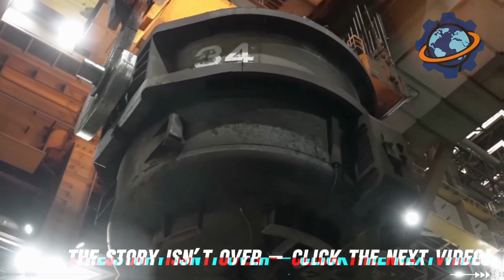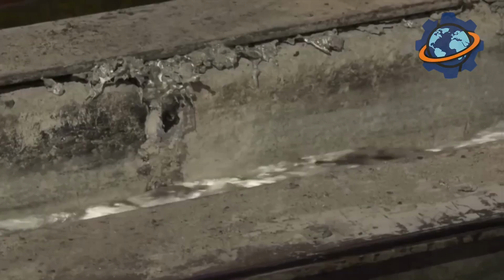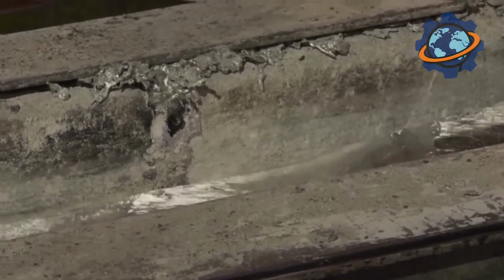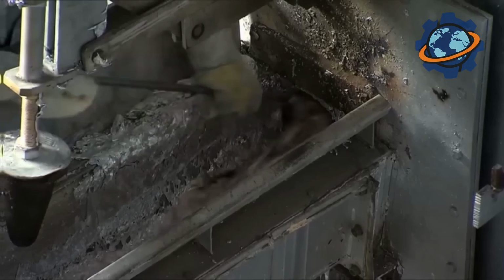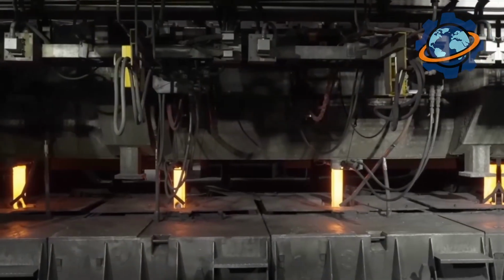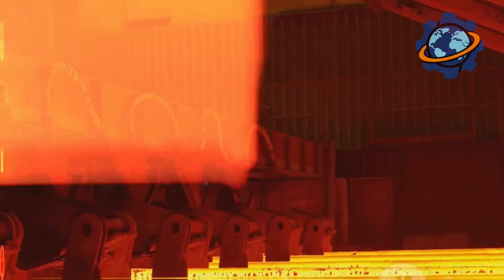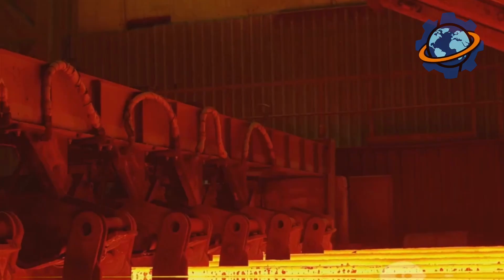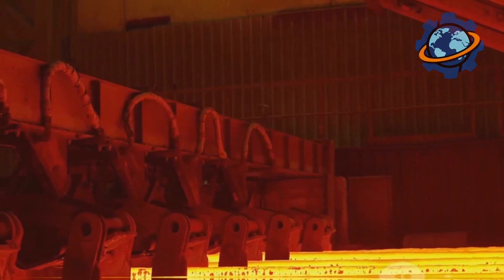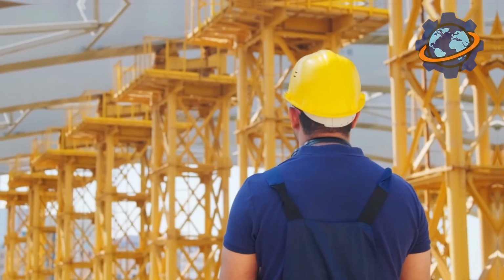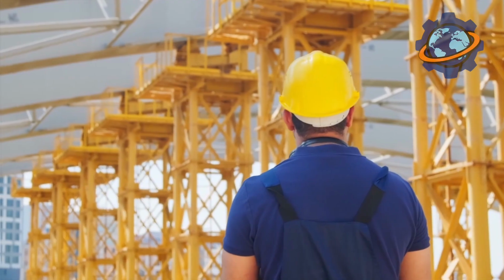Cooling determines final properties through metallurgical magic. After final rolling pass, steel enters cooling bed, where water jets precisely control cooling rate. Fast cooling creates hard, brittle steel. Slow cooling produces soft, ductile steel. Controlled cooling, varying rates across thickness, creates exactly desired microstructure. Computer systems adjust water flow based on steel grade, thickness, ambient temperature.